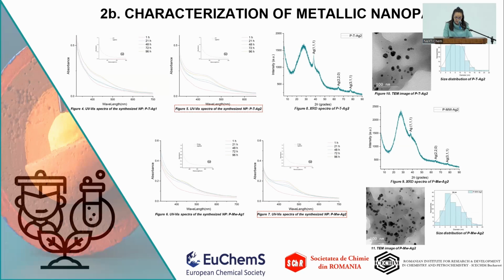And from the size distribution curve of the nanoparticles, they have exhibited on average diameters between 20 and 39 nanometers.